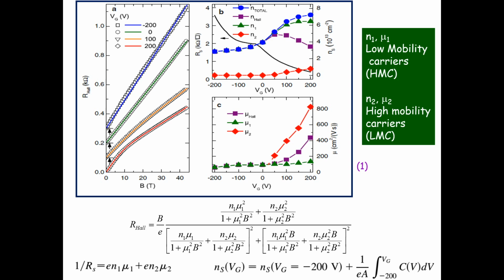So now in order to explain this nonlinear field dependence, we simply went ahead and used a two-band model. Assuming that the total sheet resistance comes from this formula, where you have one type of carriers with carrier density N1, corresponding mobility mu1, and the second one is N2 and mobility mu2. And after this analysis, what you get is, if I plot the mobility of the mu1 and mu2 type, mu1's mobility is very small, and mu2 mobility actually is at least higher by a factor of 100 or 200. So we have high mobility carriers, these ones, right here, and low mobility carriers here.